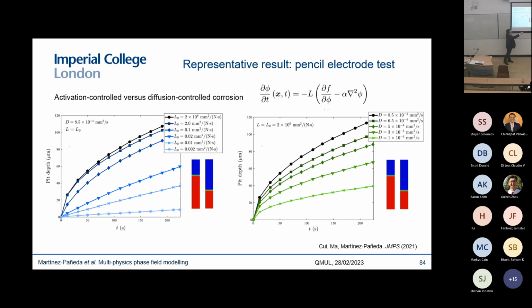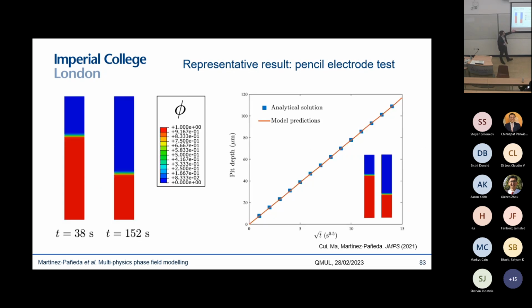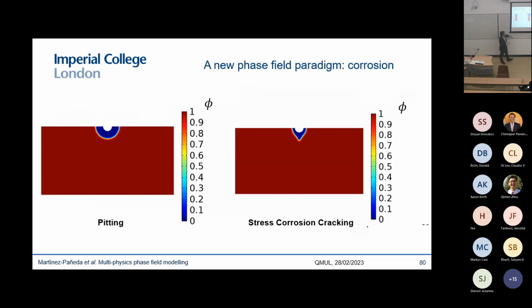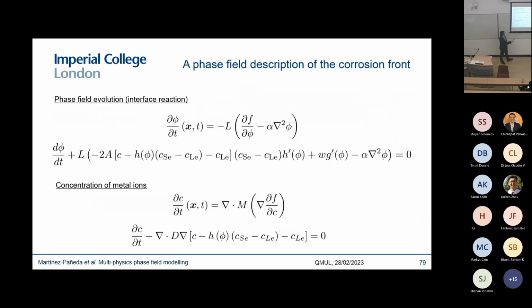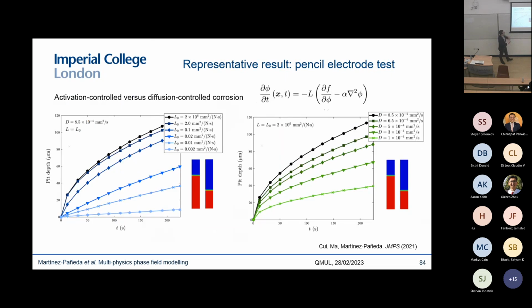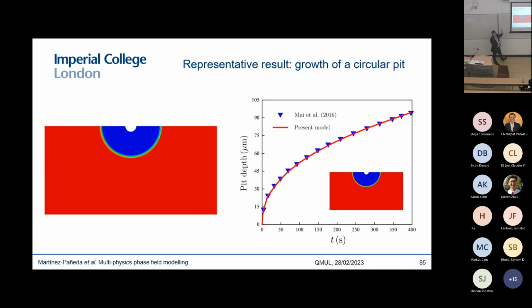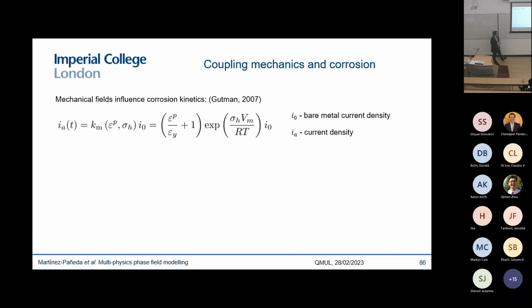This mobility coefficient here, which is quantitatively related to the corrosion current rate, and the diffusion coefficient of metal ions, which you can, again, measure experimentally. And depending on the magnitude of these values, you can get either this linear behavior of activation control corrosion, or eventually this parabolic behavior of diffusion control corrosion. And then, of course, in the diffusion control corrosion regime, if you change the diffusivity, you get different behavior. Other examples where we show good agreement with experiments.